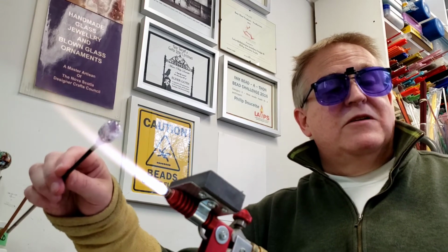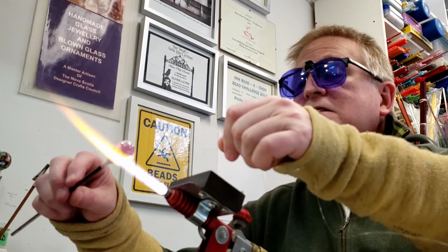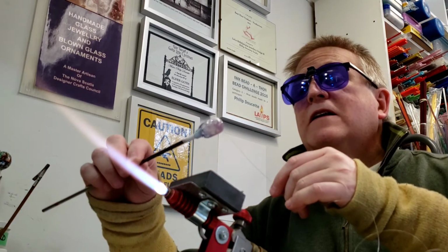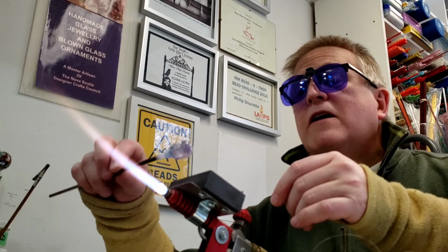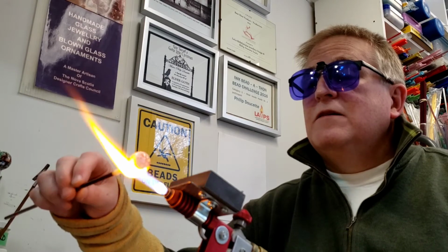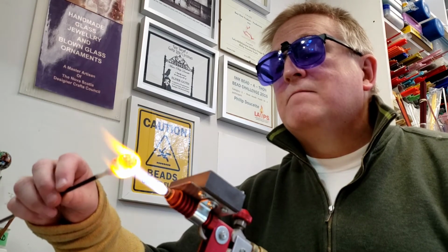I like. Now the final little touch is one that I'm quite well known for, which is using metal. Here we have a piece of 30 gauge fine silver wire that I'm winding onto the surface. This wire is so fine that it will break up into little dots all over the surface, and those dots will create bright spots with a little yellowing around them because the silver affects the clear glass and stains it. That's where the name stained glass comes from, actually, is painting glass with silver oxides. And now we can begin to create the final heating.